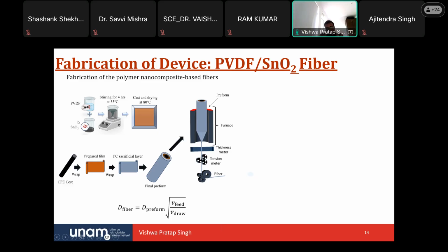We put the SnO2 in DMF for 1 hour, and also the PVDF for 1 hour. We put this on an ultrasonicator, or you can use a probe sonicator, to make a good mixture. After this mixture comes out, we mix both of them and leave it for 4 hours at 55 degrees Celsius. When you put that at 55 degrees Celsius, you will get a homogeneous solution.